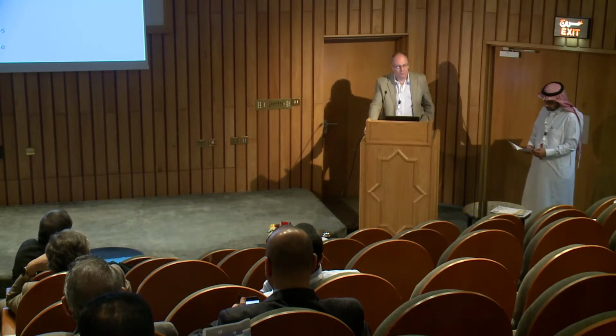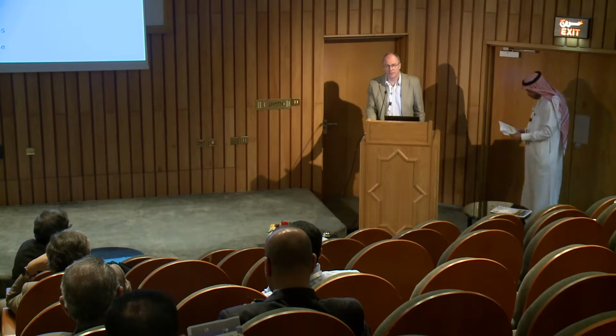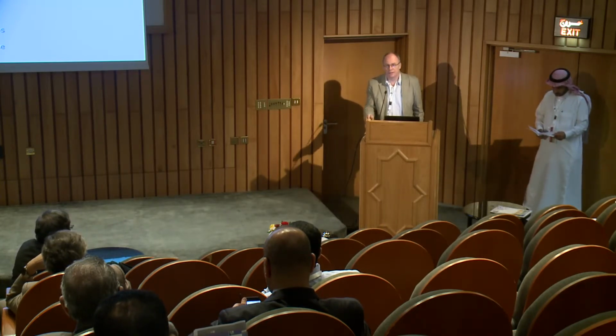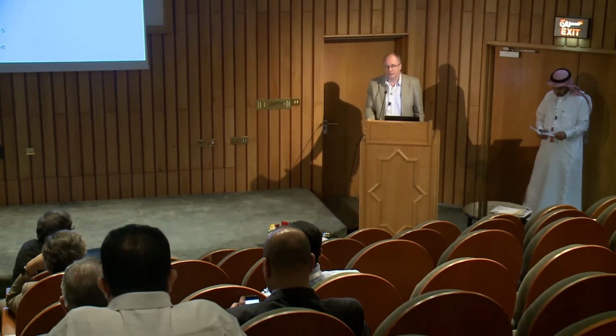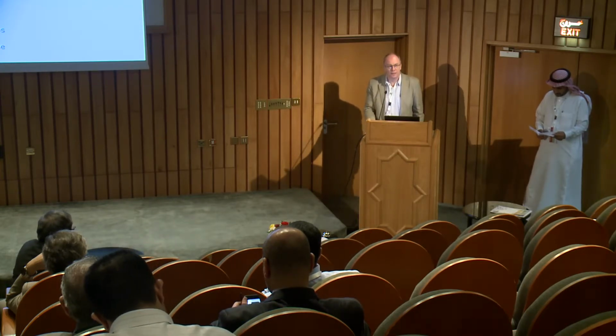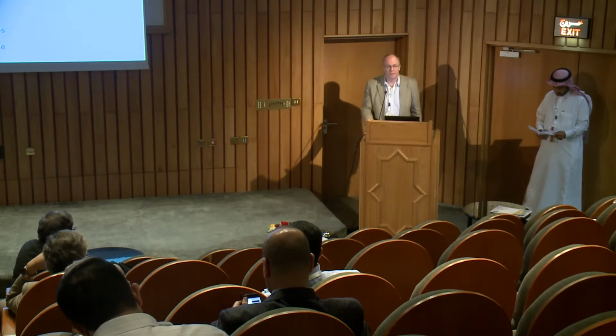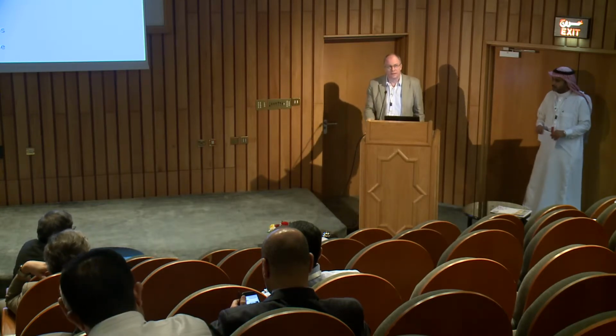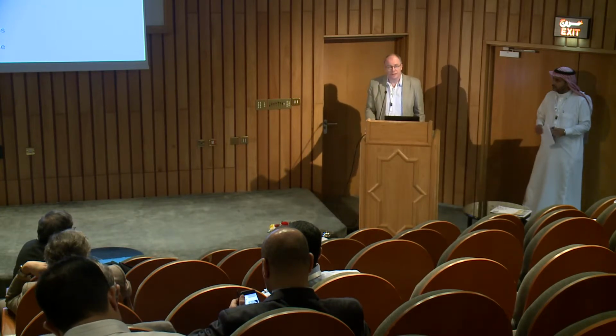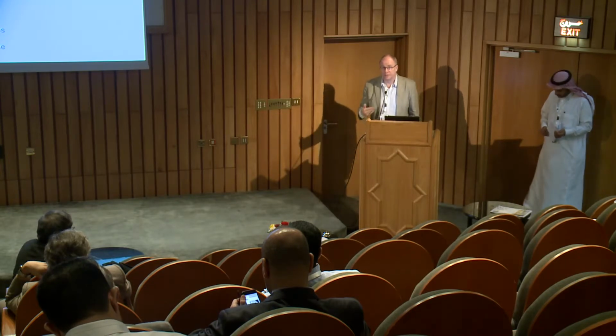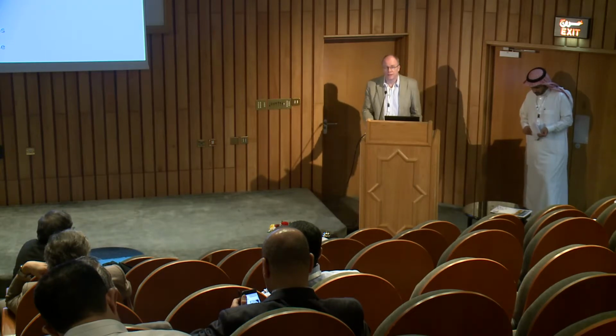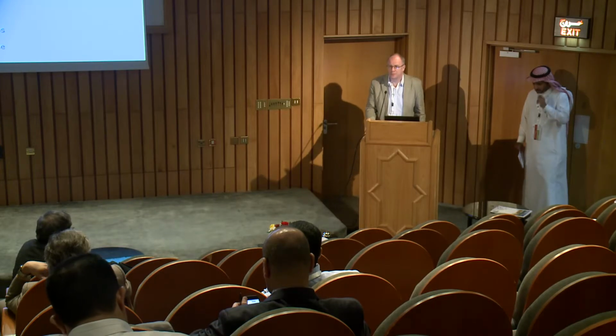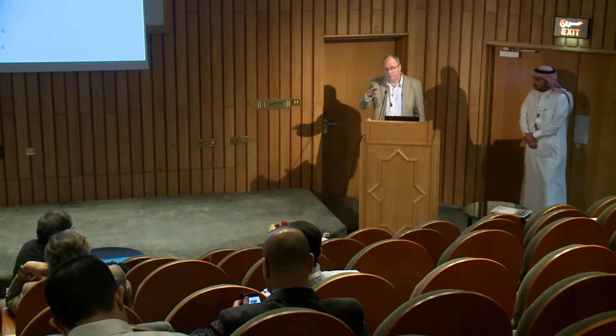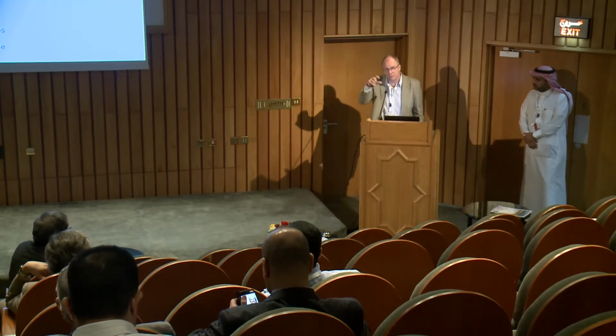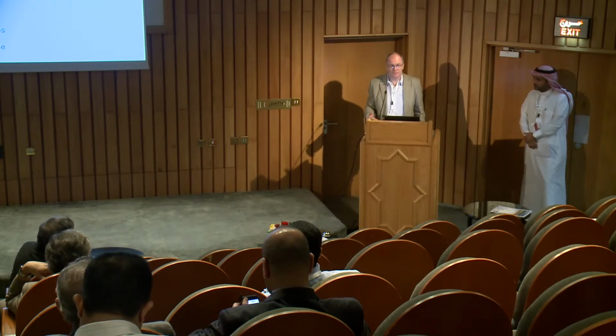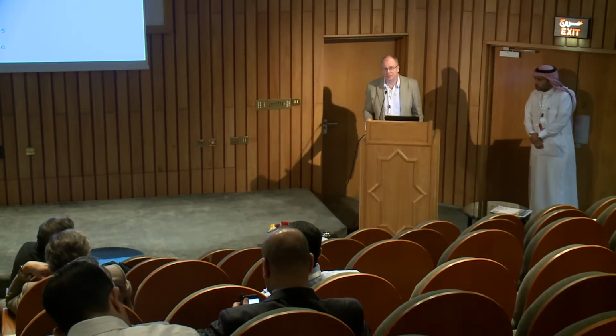The experience we have is that there are some, I would say, encouraging stability tests being presented. The most encouraging one is to simply take away the hole conductor spiro and replace it with a carbon contact, for example. There people have shown, from EPFL and from Dr. Hongwei Han at Wuhan University, that you can have 1,000 hours stable cells at 45 degrees Celsius, I think was the measurement, under continuous irradiation. We have seen at EPFL that the hole conductor material can improve stability. We have one example where, and maybe Professor Naseruddin will mention that tomorrow, if we replace the hole conductor compared to spiro, we do see an improved stability. For example, a silicon-based hole conductor. So maybe one conclusion is that the spiro is a weak component in terms of stability.